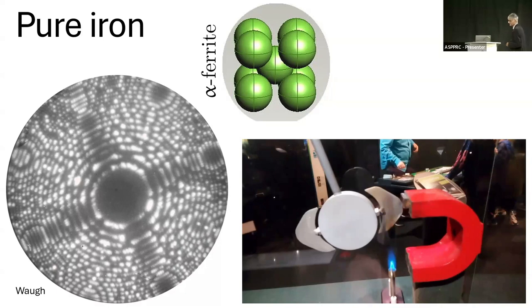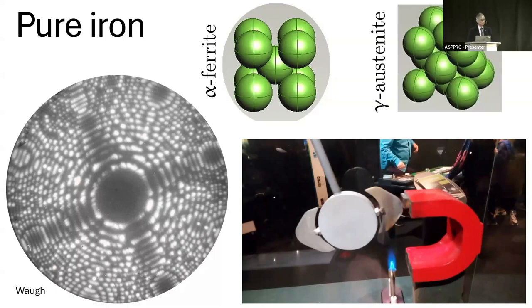and so forth. Now, if I heat this up, temperature makes disorder. So the spins would tend to become misaligned, and therefore you lose ferromagnetism above the Curie temperature. And another structure comes into being, with a little bit of superheat, which is the face-centered cubic structure, which we